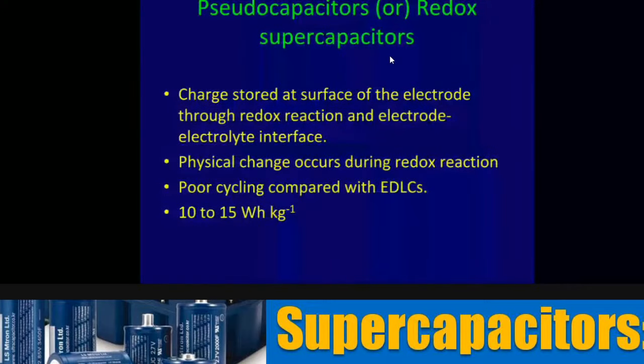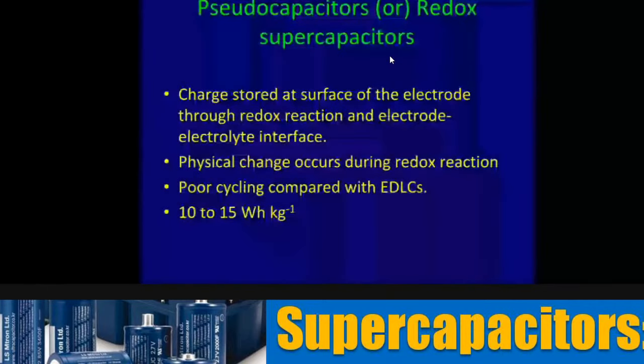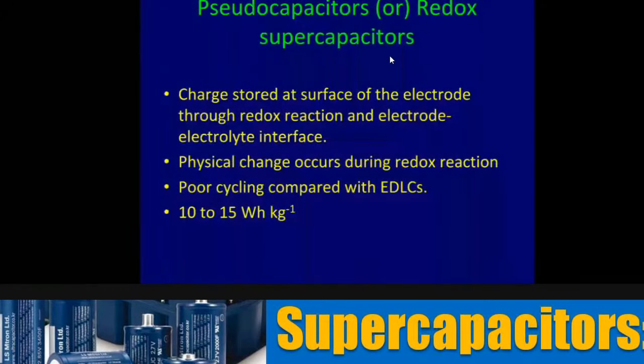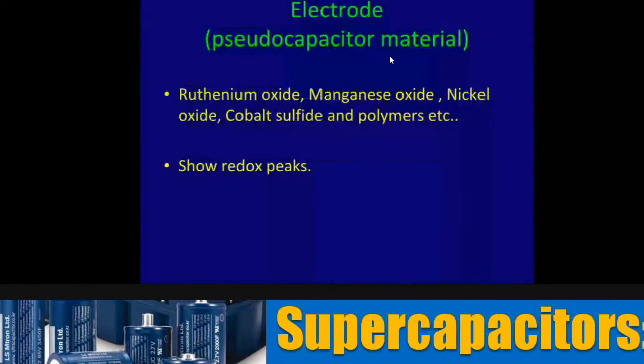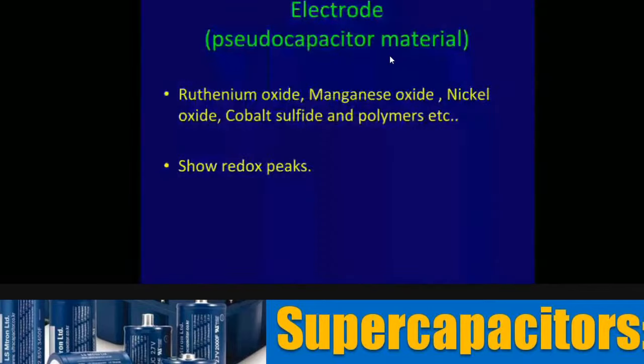And there are physical and chemical changes occurring on the electrode material. The only difficulty is the cycling performance is a little less, but today it is improved. Many have reported no degradation in the capacity. In fact, with some of the materials like nickel oxide and manganese oxide, we have seen that there is no degradation at all, and their energy densities are very high. Right. The next question, what are all the materials that are employed as electrode in these redox supercapacitors?